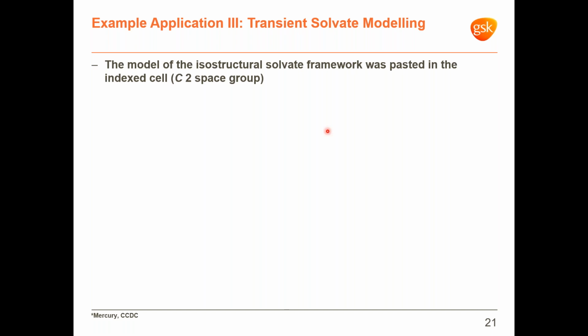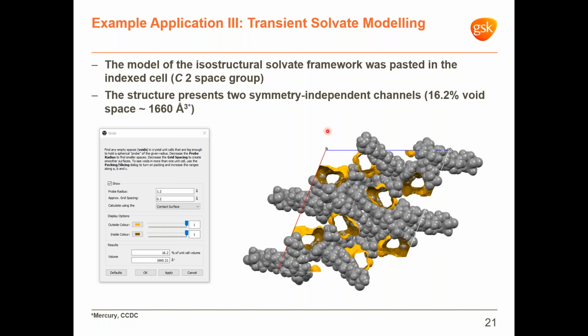Following on from the previous slide, the previously known methyl THF solvate and the suggested isostructural ethyl acetate solvate have very similar unit cell metrics, with individual axis length variations within 5%, and both crystallize in space group C2. Based on the unit cell similarity, we could transfer the dry structural framework from the methyl THF structure into the unit cell of the target ethyl acetate solvate.